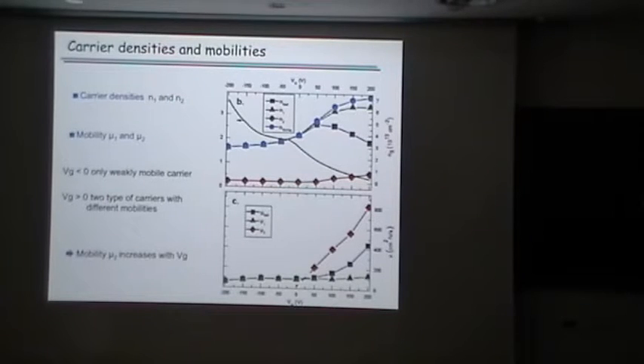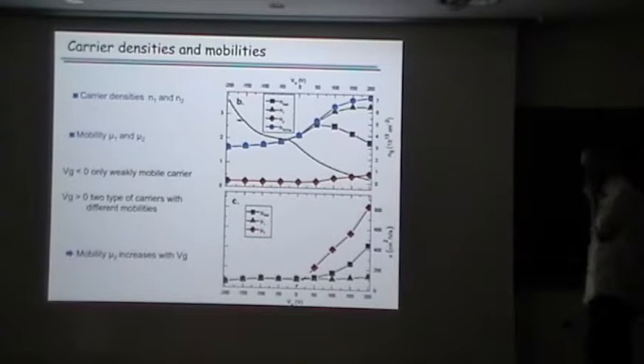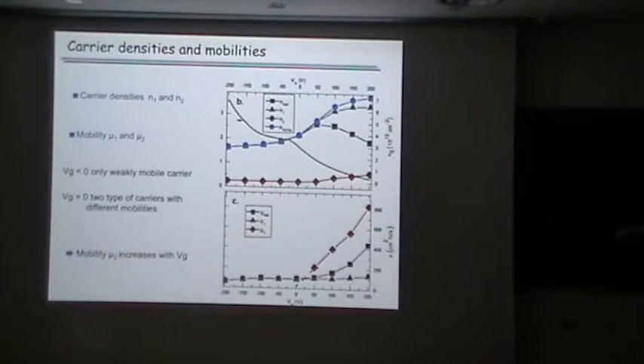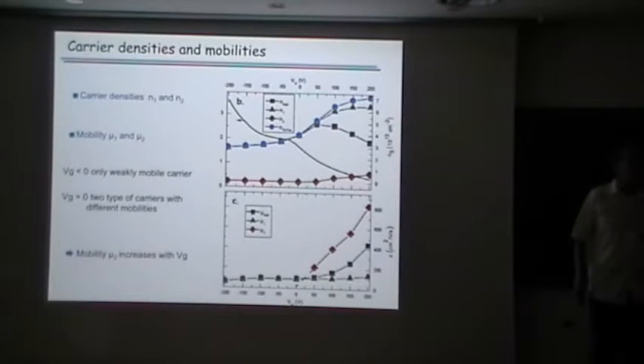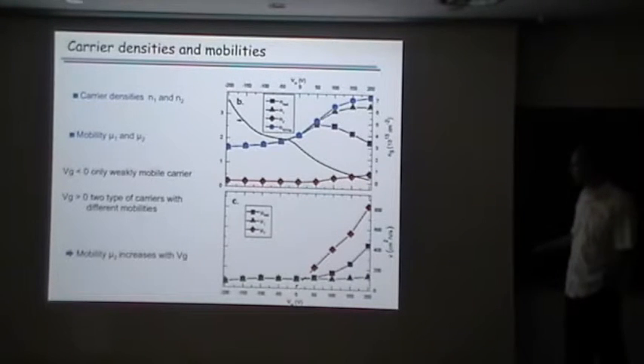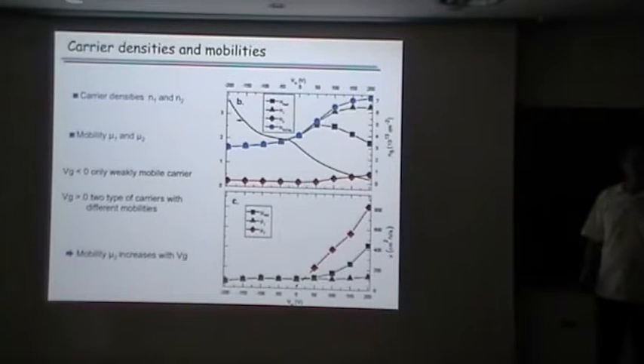And this is, for instance, the number of carriers. So this is the Hall effect at low field that I presented to you before, on this sample. And here, most of the carriers are very low mobility carriers. The ones you have at negative voltage keep increasing at positive voltage, so you put in more and more carriers. But around zero, you have a lot less, but very mobile carriers. And if you look at the mobility, this is the total you get. You have a fairly constant mobility with the gate voltage for the massive carriers, but you have a mobility increasing very fast and rather linearly when you put positive voltage. So clearly you put light carriers in the system only at positive voltage.